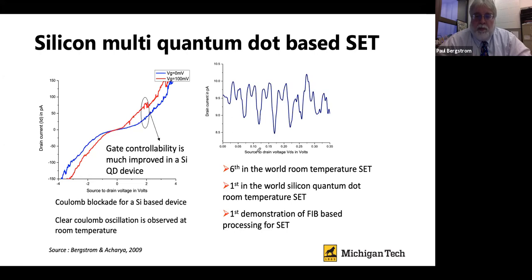So there is some embedding of the ion from the focused ion beam that actually shows up in the behavior of the device. So these characteristics are a little bit complicated. This shows a current versus voltage, and this shows what I noted earlier, this Coulomb oscillation, where we see a periodic cycling of the current. And that periodic cycling of the current is related to these very unique quantum states that are exhibited in the system. But you also notice that it's a kind of a complex characteristic.